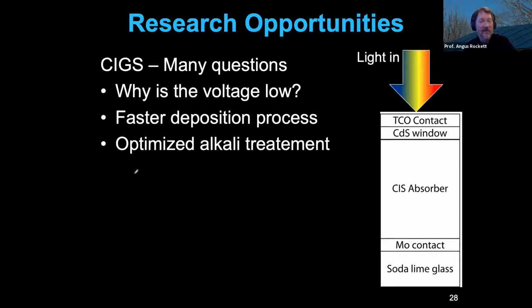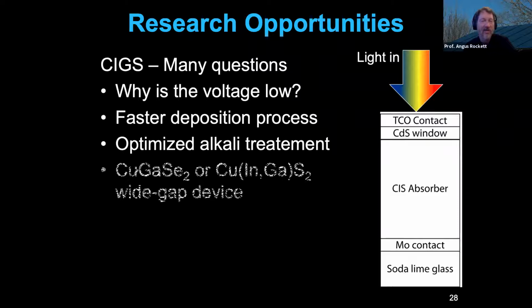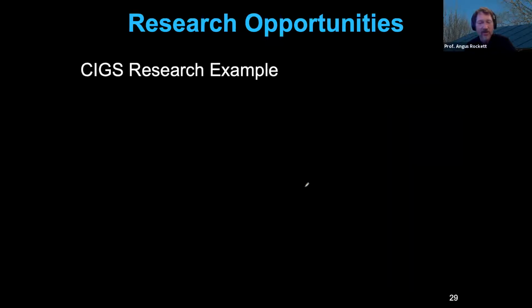We need optimized treatments because it turns out that alkali metals help the materials, and we need to figure out how to improve that. We'd really like to make a wide gap device, and the current devices are narrow gap by comparison. They're very similar to silicon. So we'd really like to have something like copper gallium diselenide or a sulfur compound to get a wider gap material. So just to show you a research example, what we've been looking at, I mentioned that speed is really important in the process tool.